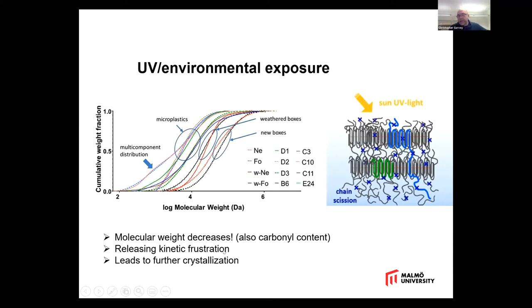I started off by introducing this material, the melt process, as kinetically frustrated. What this does is release this kinetic frustration, and this material starts to crystallize. And this is the underpinning process of the environmental lifetime of materials. I'm not going to talk so much about this, but there is also an important chemical change, and that's the increase in oxidized polyethylene, or the carbonyl content. That's another story that I really won't be delving into in much depth in this talk.